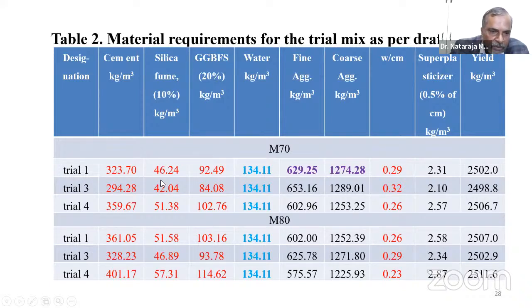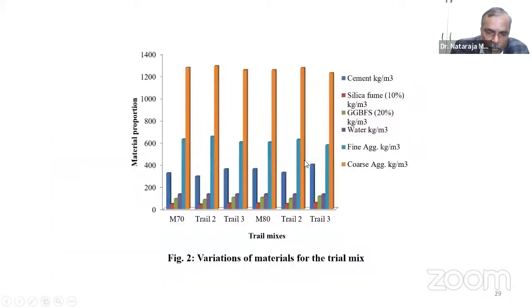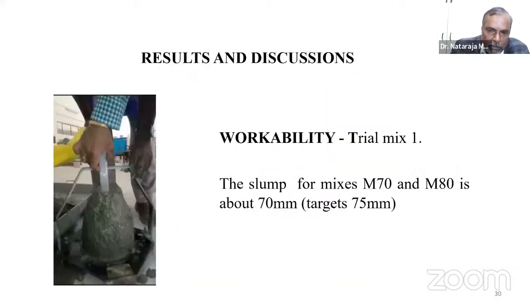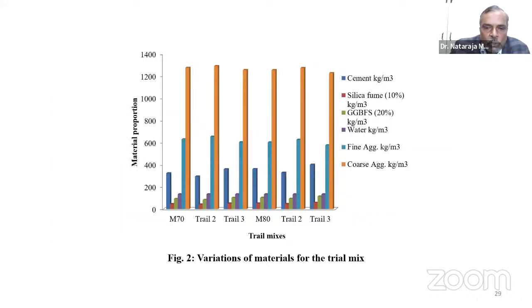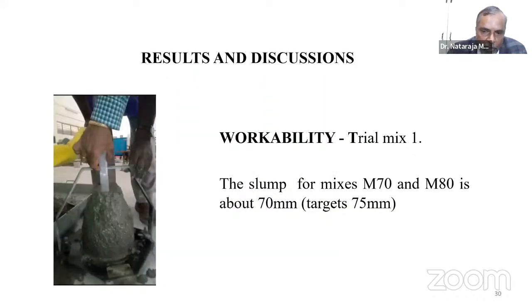And kindly see the increase and decrease in the cementitious system. And all these things we need to again observe in the form of a graph. And also you need to develop what are called the water cement ratio graphs to appreciate what exactly the variations that are likely to come. And kindly see, we have designed for 70. 75 mm was the target slump, but we are really not bothered about the slump of concrete. Even if it is 50, we are not going to bother because we slightly increase the admixture dosage and we get the 75. By chance, if it is 100 mm as against 75, we need to decrease the dosage of the admixture so that any target value of the workability can be achieved. And this is not a design parameter as far as our work is concerned. So any change, I can adjust it because I can change the dosage of the admixture.